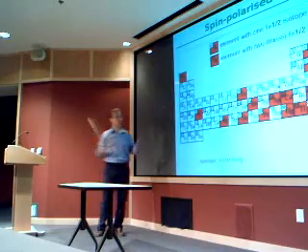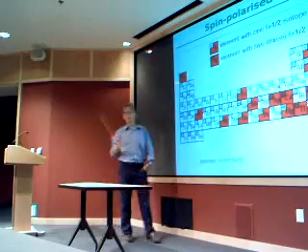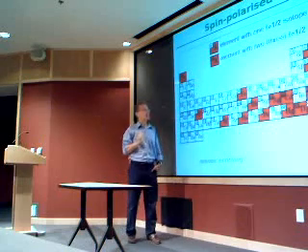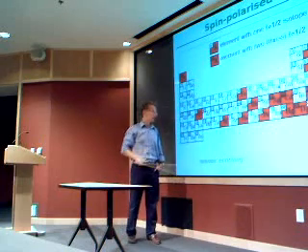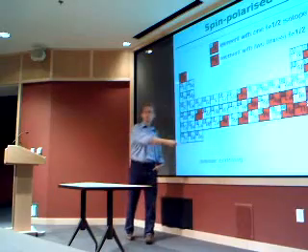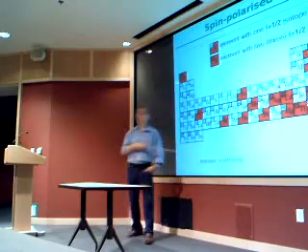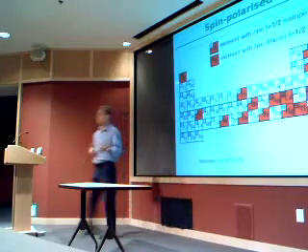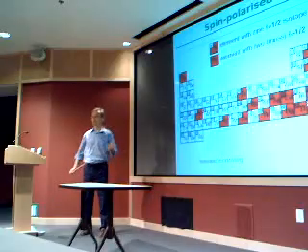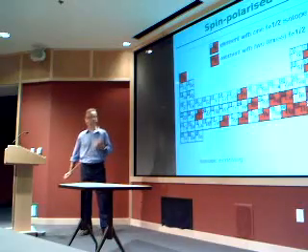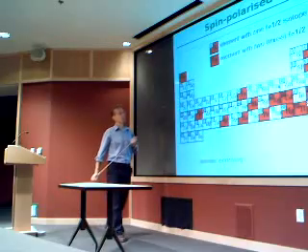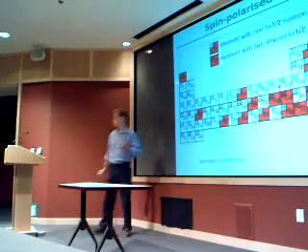So sometimes the signal is too weak, because you have only 1% of the carbon in the sample that is active for NMR, so one has to use isotopic enriching. When one prepares the material, one inserts more of the isotope which is active, which has a nuclear moment.